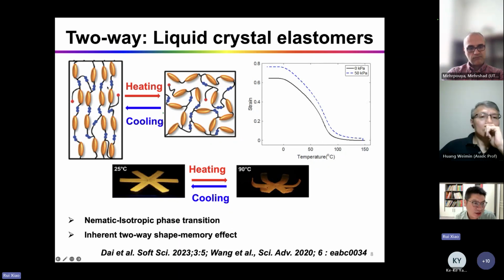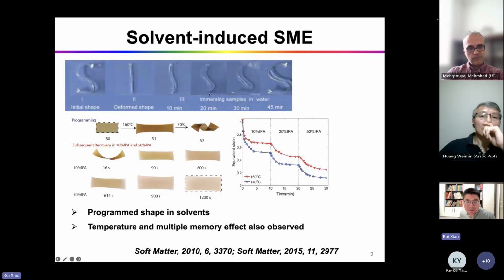The mechanism is the nematic-isotropic transition. So at low temperature it's nematic phase, at high temperature it's isotropic phase. So if you heat it, it changes shape due to the chains going from the orientation direction to random directions. So all these parts are called temperature memory effect, or heat-responsive SMP.